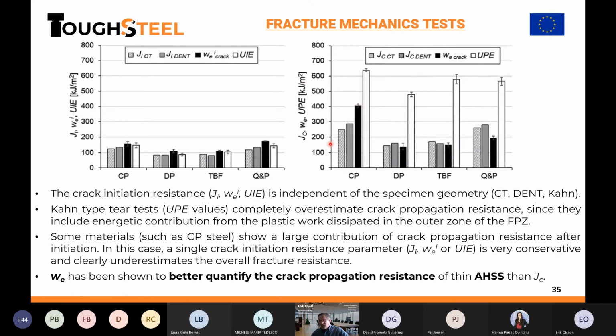It happens in these materials, complex phase or similar materials, that have a large energy contribution from propagation. So if we cannot properly capture the energy used in propagation, we are not properly estimating the toughness. So for the materials we are really interested in, the ones that have higher energy absorption, the J integral underestimates. It is really a conservative way of measuring properties.